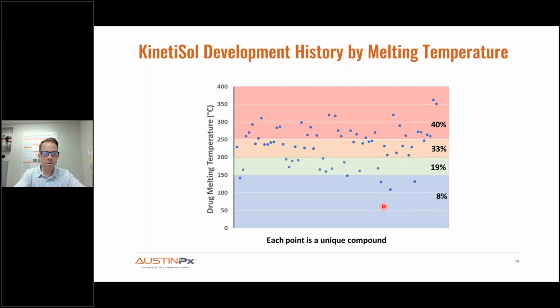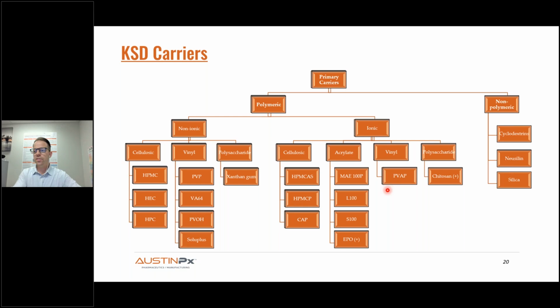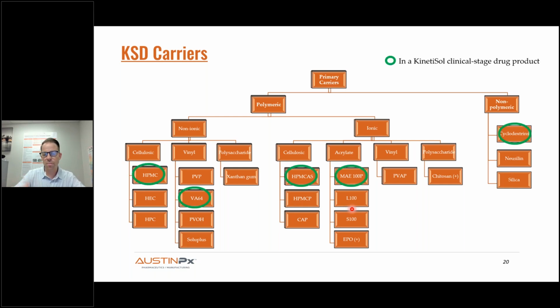And then you look down, we've worked on some fairly low melt compounds as well. So melting temperature really doesn't impact the applicability to kinetisol whatsoever, but it definitely limits what you can do with melt extrusion. And then let's talk about the formulation design space. There are all of these various primary carriers available for ASDs, ranging from polymeric, like non-ionic polymers and ionic polymers, and then getting into even non-polymeric materials. And there's various chemistries under these categories as well, and subchemistries and subgrades. There's so many polymer options out there, but yet there are very few that have actually been commercialized. And this is reflected in some of our clinical stage kinetisol products. We really stick to the polymers that have been tried and true.